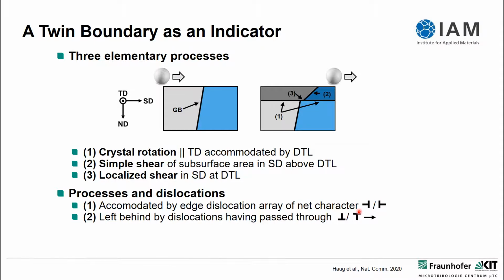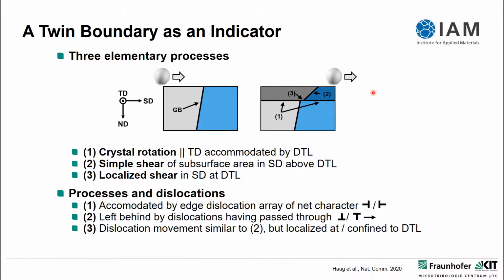The second one is edge dislocations oriented either like this or like this, because they just pass through the material parallel to the sliding surface. If I move the mouse like this, it just moves through here and doesn't leave any trace behind other than moving the twin boundary. Without the twin boundary we would not know of this process, since there's no way post-mortem to know about this. It's the same type of dislocations, but highly confined where the dislocation trace line is, that is responsible for this highly localized shear.